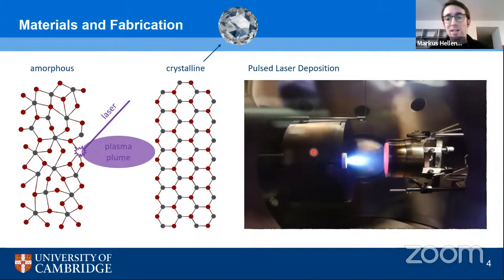However, as hard as we may try, it's very difficult to make such perfect materials, and usually there are always some defects in the material, so dislocation, something like this. The materials that we're looking into are mostly oxides, so compounds of metals, transition metals, and oxygen. In this schematic here, I represented oxygen as the red dots, and one of the most common material defects in oxides are oxygen vacancies. So that means in this beautiful crystal lattice, there are some sites where there should be oxygen atoms, but they're missing. So these are oxygen vacancies. And while I called them material defects, we actually want to use these defects in making the energy efficient memory. And I'll show you how just in a second.